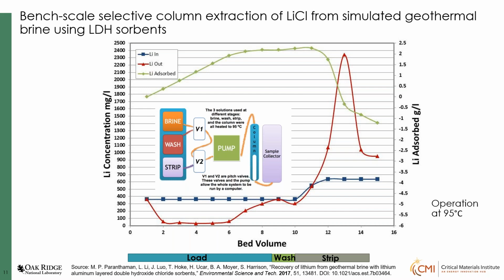The other thing is this operates at 95 degrees, and the lithium chloride is separated instantly. So you can do a continuous process like a column extraction. Within a few hours, you can do it, compared to the 18 months we saw in the case of evaporation in solar brines. So that's where this opportunity comes in. Next slide, please.